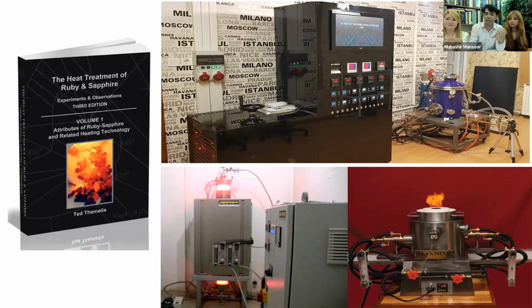You have propane coming in from one side, you have oxygen coming in from the other side. If you don't have the necessary backflow stops and all sorts of those things, then it becomes quite an explosive mixture. If there is anyone interested in doing these experiments by themselves, I do not recommend going for an oxypropane furnace at all. Just go for a beautiful electric furnace. It does the job much more elegantly as well. Now, this on the top is the system that we are using, that we have developed. And we try to do these in all sorts of different environments. We do all sorts of different atmospheric conditions and so on. But we'll go deeper into that in a bit. I highly recommend the book by Ted Themelis on this issue very much, because it covers a lot of different furnaces.